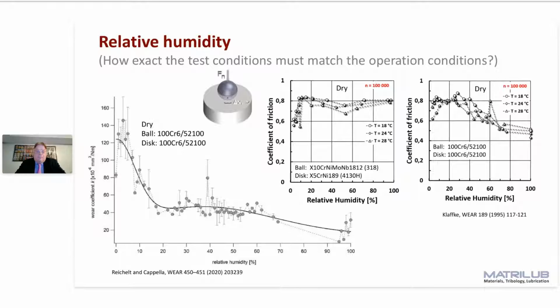Here on the top right, you see also dry oscillation, two different materials, stainless steels. Until 10–15% of humidity, friction is in this case independent, but when it gets dry, friction drops. This can also be embarrassing in application when you sell something into a very dry region. You have designed a frictional contact with a friction coefficient of 0.8, but in this dry region it drops down to 0.5. Or in the other case for ball bearing steels, when it gets humid, you have the drop in coefficient of friction.